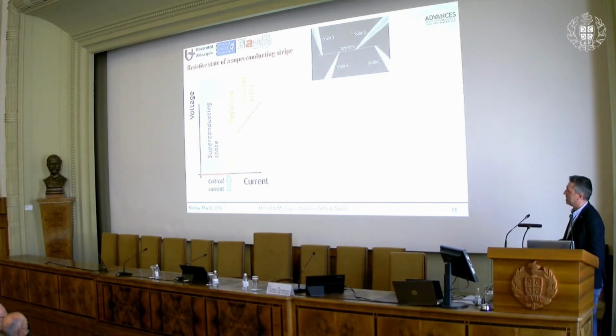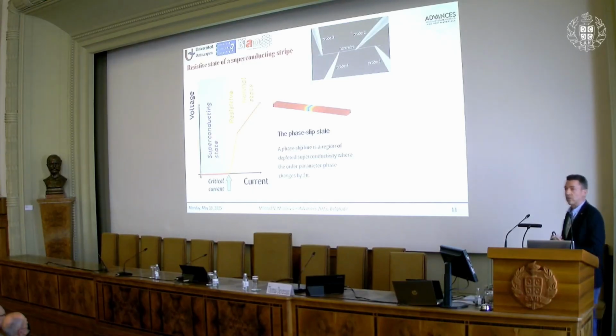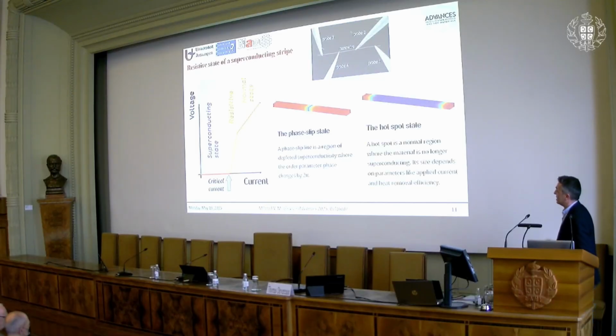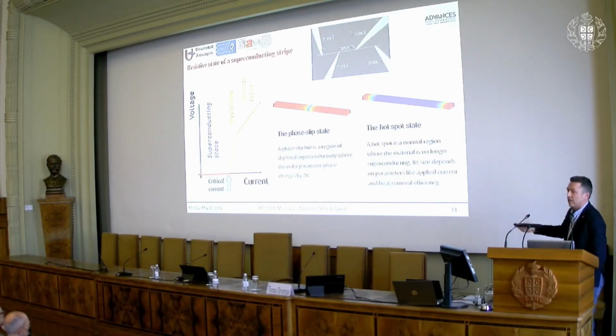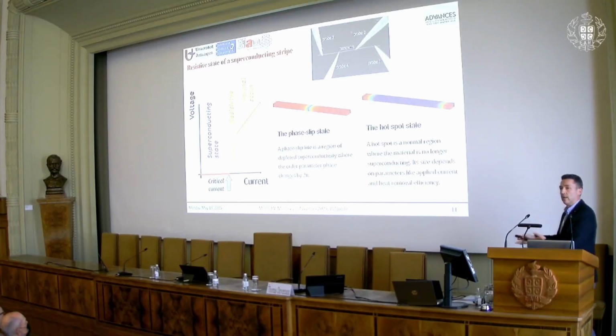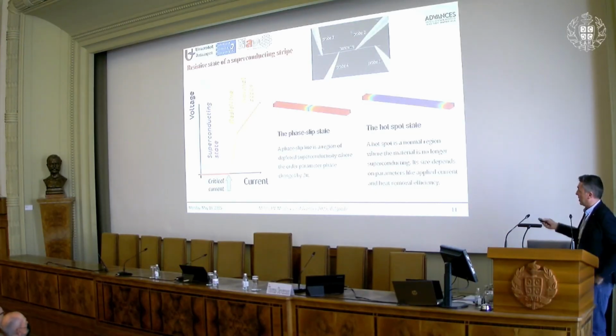So what is this resistive state? Well, there are two possibilities. There is a so-called phase slip, which means that there will be a thin region, about a coherence length wide, of suppressed superconductivity, where the phase of the order parameter from one side to the other will change by 2 pi. That's why it's called a phase slip. Another possibility is the hotspot state. It's again a similar thing, similar dynamics, but this normal state is going to heat up the superconductor, and we will have a larger region where superconductivity is destroyed. From resistivity alone, you cannot tell which one it is, but from the dependence of resistivity on temperature, you can experimentally determine which one you have. But these are the resistive states that I will be talking about in the rest of my talk.